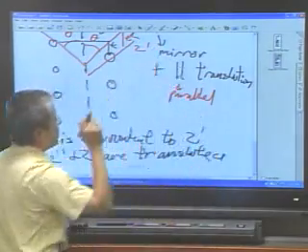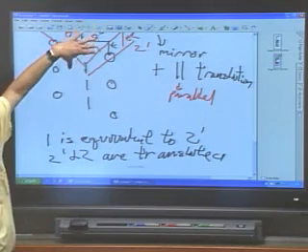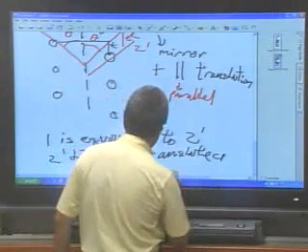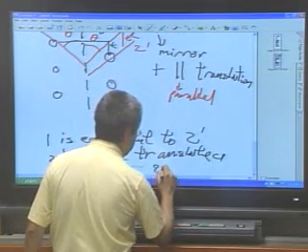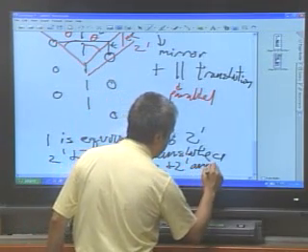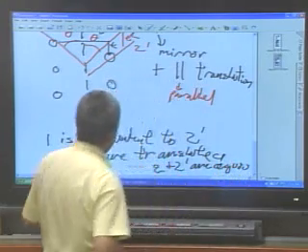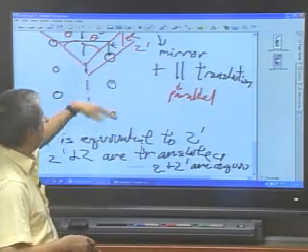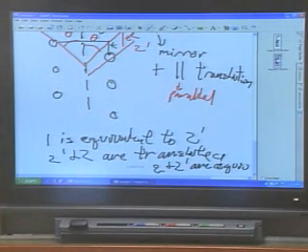So we know from the other statement, if I measure the property in the 2' direction, and I measure it in the 2 direction, all I'm doing is moving the crystal, they should be exactly the same. So by that argument, 2 and 2' are also equivalent. And as a result, since 2' and 2 are equivalent, 1, therefore, should be equivalent to 2. Okay. So 1 is equivalent to 2' because the two directions are related by the symmetry operation. 2' and 2 are just simply translations of each other, so therefore they have to be equivalent.